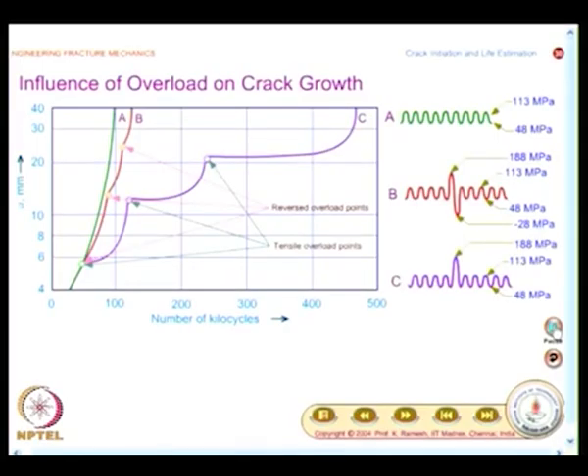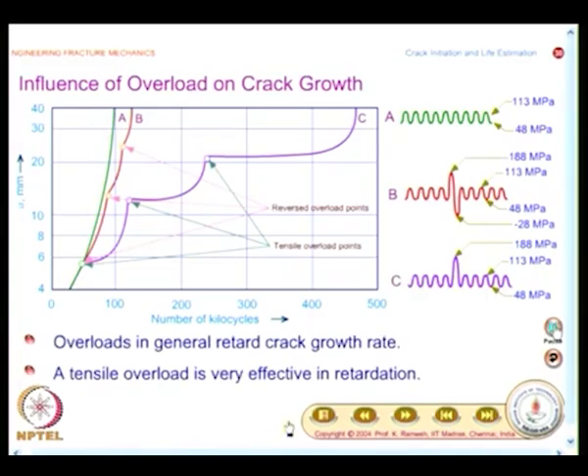What way we are going to look at is the plastic zone would be much larger when I have an overload, the plastic zone would be much larger, that has helped this retardation. So, your modeling of the plastic zone is very important, and recognizing when you have a cyclical load, you are going to have a residual stress ahead of the crack tip, and when I have an occasional overload, I will have a very large plastic zone, and this crack has to wade through that plastic zone. So, that in a sense retards the crack growth, and you have a model for that, and this model is proposed by Wheeler. The details of it we would see in the next class.